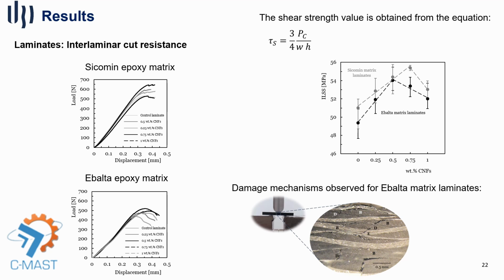In terms of interlaminar shear strength properties, the addition of carbon nanofibers reinforces the properties of carbon laminates. The interlaminar shear strength value for those using the Sicomin matrix reinforced with 0.75% by weight of carbon nanofibers is about 8.6% higher, while for the Ebalta matrix reinforced with 0.5% by weight of carbon nanofibers, it is about 9.4% higher.